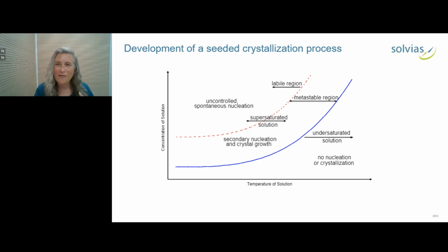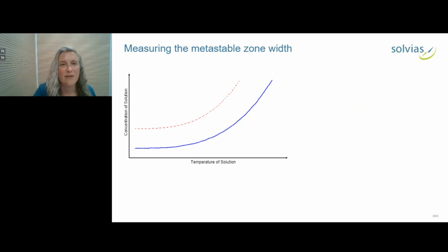And here you have some supersaturation, so you can crystallize, but there's not such a strong driving force for spontaneous crystallization. And so you can develop a seeded process where you lower the temperature and seed. And if you stay in this metastable zone, you can get a controlled crystallization of your desired form. And we can measure the metastable zone using turbidity probes, or also other probes that you'll see on the next slide. And the concept is quite simple.